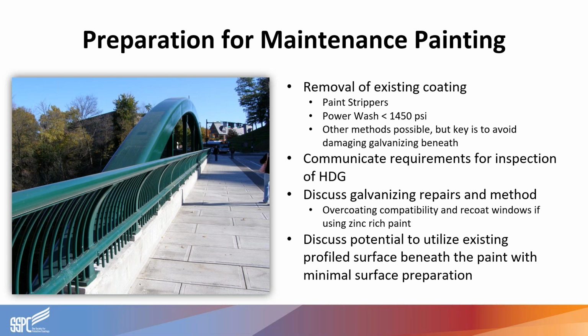If we're looking at a full recoat, removal of the existing coating, obviously there's a lot of ways to do that, but you would want to consider methods that are going to preserve the hot dip galvanized coating. And so you can use paint strippers or power washing as long as pressures are held below 1450 psi so that you avoid damaging the coating.